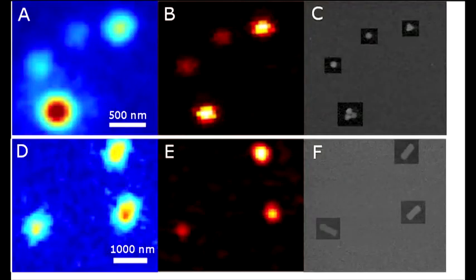Because the scattering signal scales with the volume squared and the absorption signal scales with the volume, the absorption measurement is more sensitive for small nanoparticles.